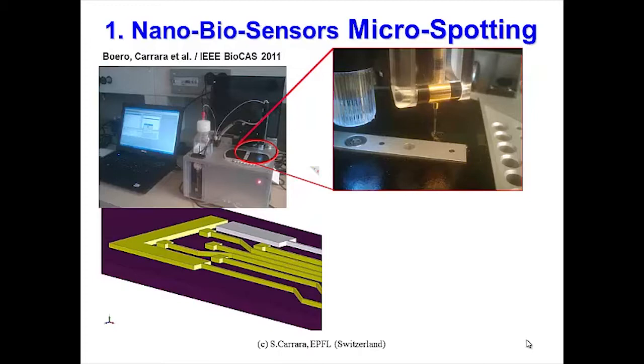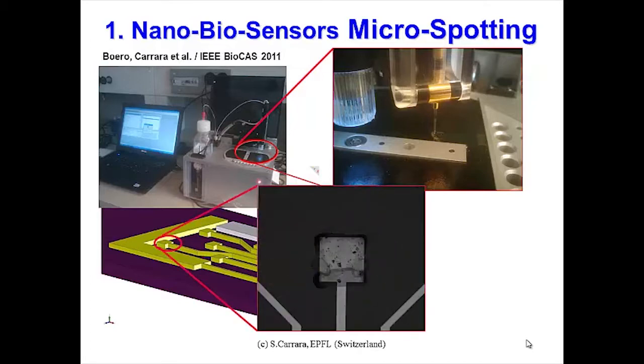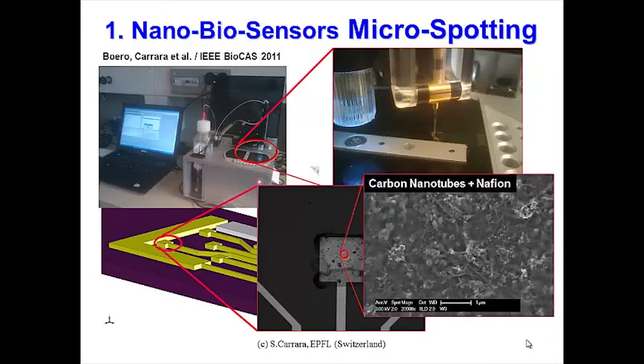The only problem here is that this technology is based on water solutions, while carbon nanotubes are highly hydrophobic, and in water they stick together. You no longer get the forest I showed you before, but an enormous bundle of carbon nanotubes. So the solution here was to monodisperse the carbon nanotubes in Nafion, in order to have a monodispersed solution of carbon nanotube and Nafion in water. And we succeeded. You can probably recognize some drops with multiple droplets. We succeeded in covering our electrode with our carbon nanotubes. This is a scanning electron micrograph where you can probably recognize some carbon nanotube fibers. Meanwhile, you also see some Nafion particles.